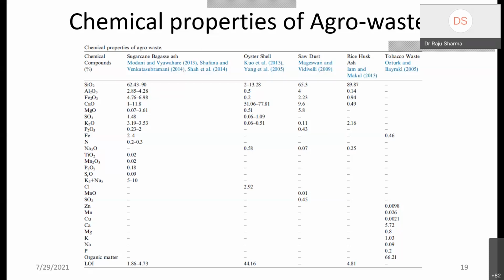You can see there is a higher amount of calcium, right? There is a higher amount of calcium. So if there is a higher amount of calcium, that can be representative of a reactive filler or reactive supplementary cementitious material, right? So the behavior of this particular product is more dominant towards the hydration product formed by the calcium rather than the silica. So it is more dominant towards the calcium. It increases the calcium content of the paste.